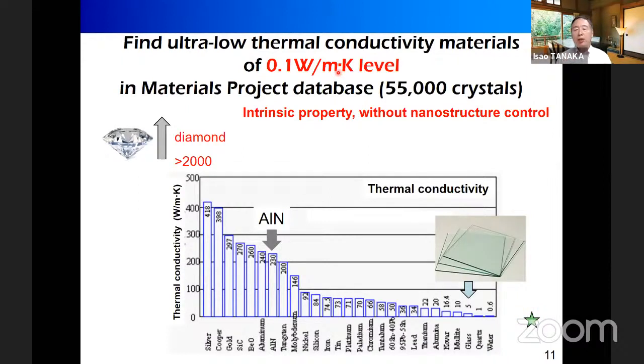Our question is whether this kind of material exists among the known materials registered in the Materials Project database, which at that time contained 55,000 crystals. And if it exists, the next question is which crystal shows such a low thermal conductivity. By the way, quite often people use nanostructure control to decrease thermal conductivity, but what we are going to discuss is the intrinsic property, without nanostructure manipulation or structure control. So please remember this 0.1 watt per meter Kelvin. This is our target.